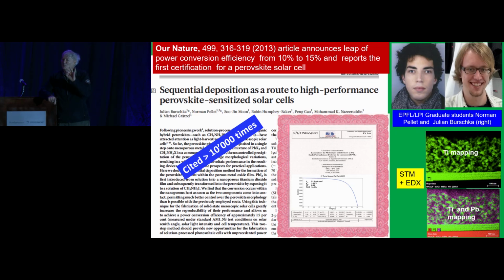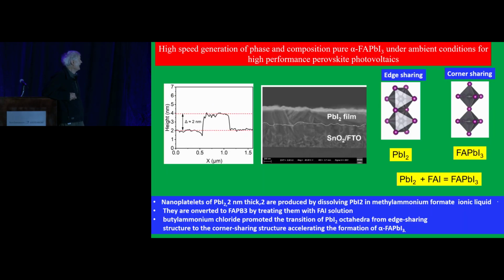And the conversion worked so well because you would use the precursor. The lead iodide would partially fill the pores. There was a high surface area exposed of the lead iodide. And so the conversion reaction would go on very quickly. However, the real interest is to make compact films, not mesoscopic films. And so here's some unpublished work, which I will now go into for 5 minutes in more detail, to give you a taste of our present efforts.